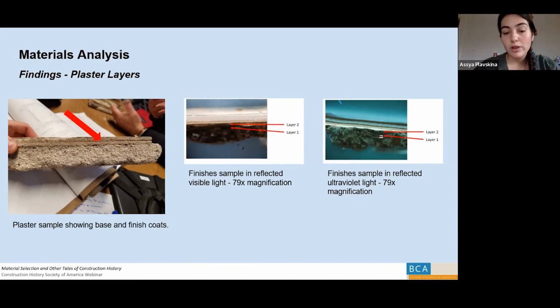So they applied one layer of finish coat, paused the work to finish everything on the exterior and everything that Upjohn requested, and then came back and applied a second layer. And we can see the same subdivision in our photo micrographs there. What we're finding in our analysis is that the first layer had cured before the second layer was applied. So it was too long of a time period. And that caused, in some places, but not all, a weak bond between the two layers. And so this outermost layer of plaster finish coat was actually separating from the bottom layer of the finish coat.